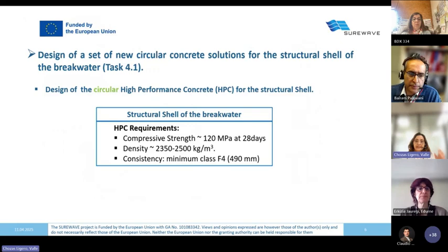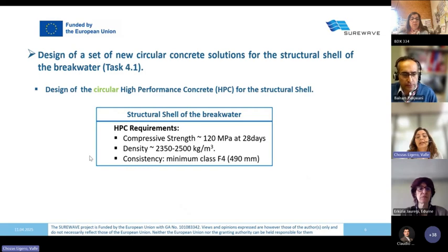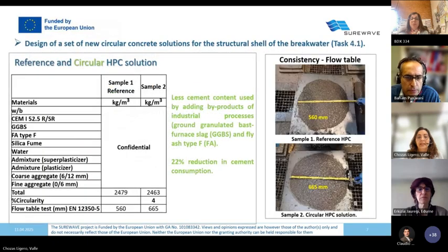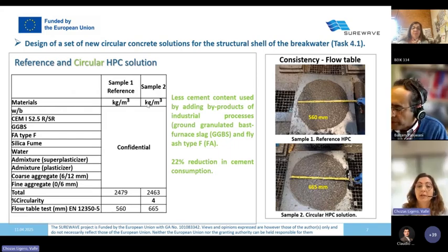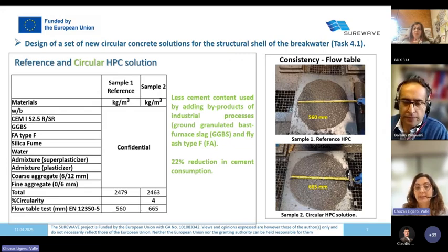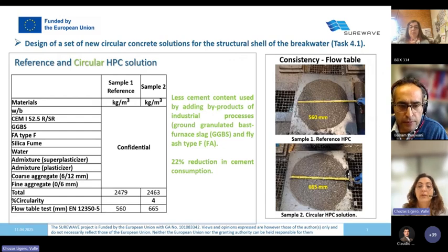Regarding high performance concrete, the set requirements were 120 megapascal at 28 days, the density of conventional concrete, and consistency of minimum class F4. The principal objective in this type of concrete was to reduce the amount of cement by using other products like GGBS, ground granulated blast furnace slag, and fly ash type F. We reduced the cement by 22% by weight.